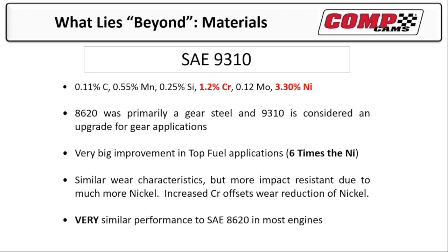Now, normally nickel really hurts the wear characteristics. So 9310 has the added chromium, which offsets the wear reduction of nickel so that you really wind up with almost identical performance of 8620 and 9310 in camshafts. The only place this wouldn't be true is where you see really, really drastic bending. Maybe a flathead Ford with a little 800 barrel that has only 3 bearings, so it's got really long spans. That would be a place where it'd use 9310.